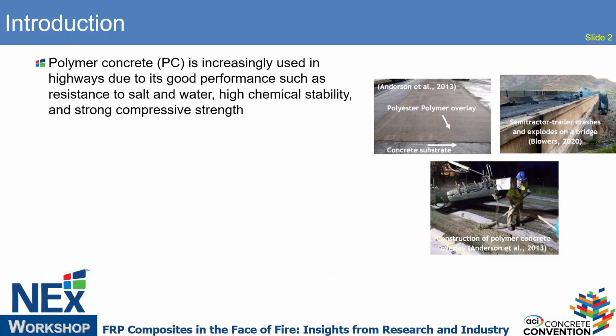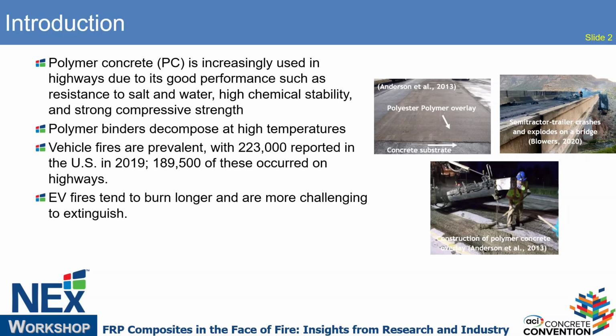So the polymer concrete is increasingly used in highway structures and as the overlay to protect the concrete bridge decks due to its good performance, such as good resistance to salt and water, high chemical stability, and strong compressive strength. While the polymer binder decomposes at high temperatures, vehicle fire is prevalent. Even in 2019, more than 223,000 vehicle fires were reported, and more than 180,000 occurred on the highways.